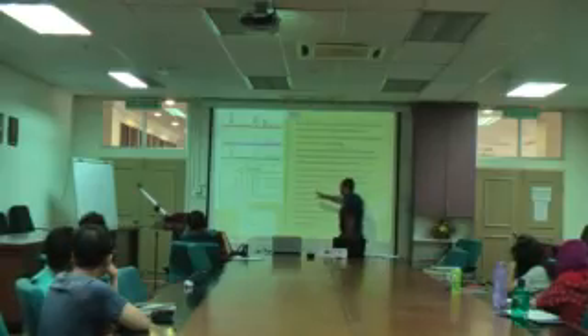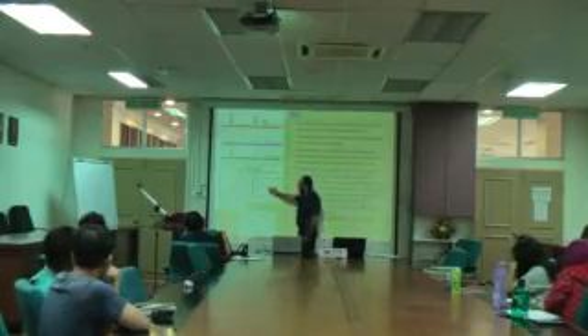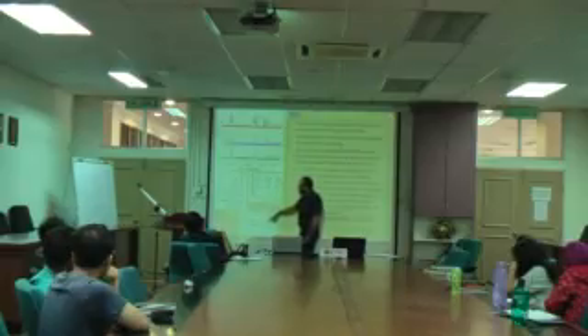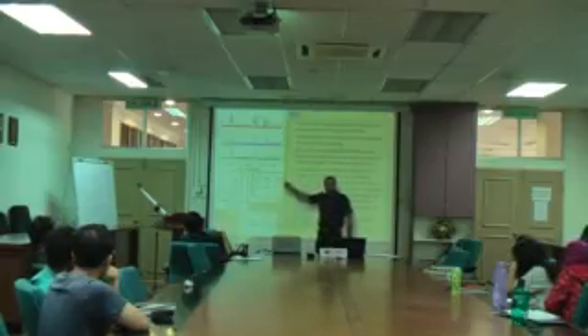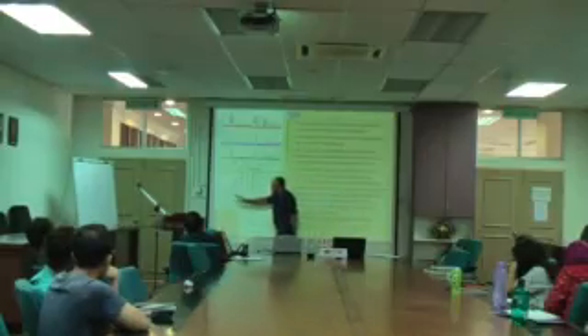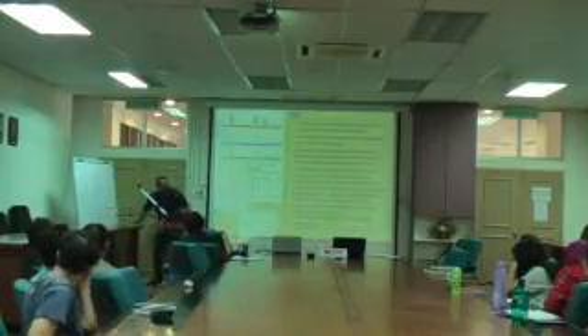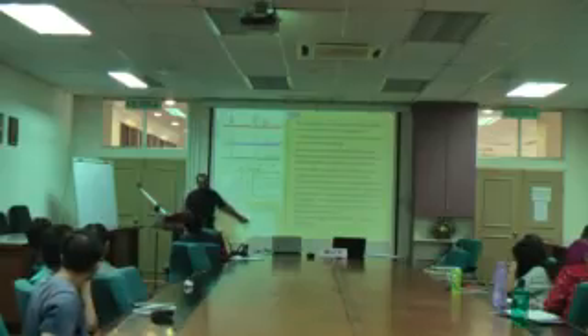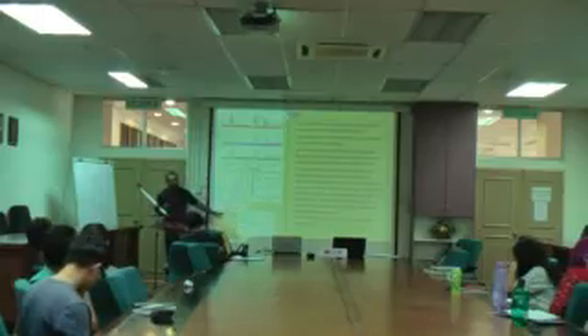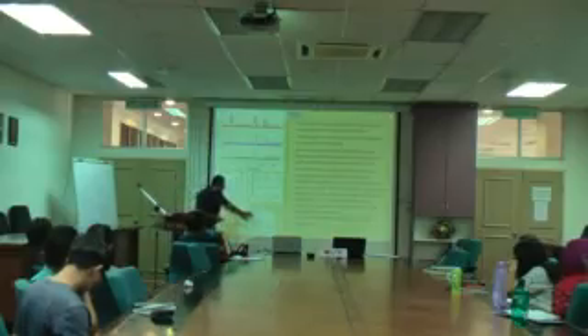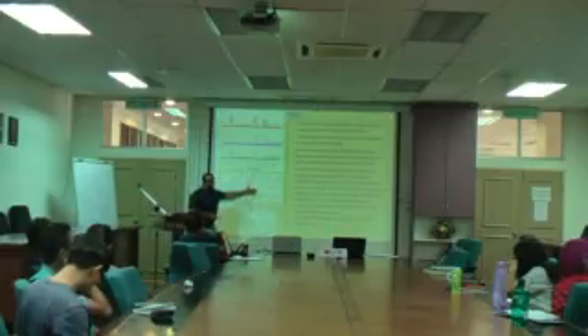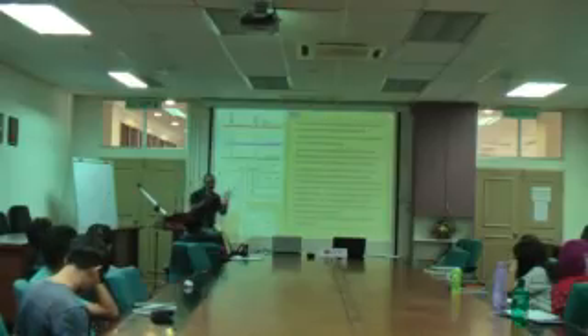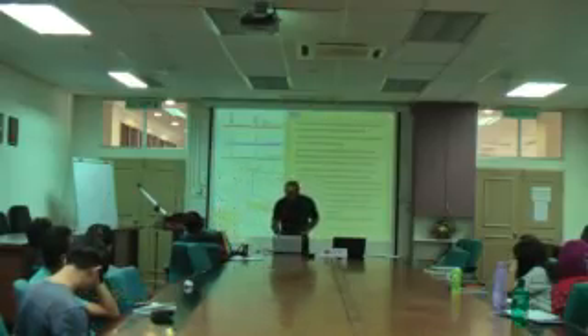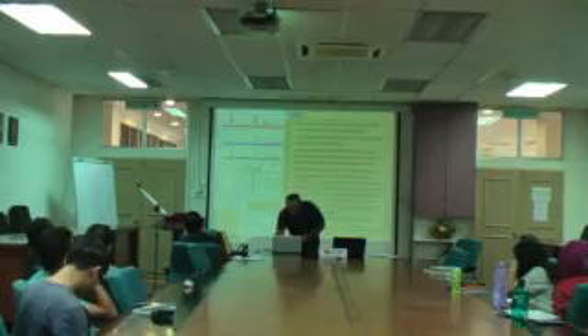And also for Scherrer, these are two different characterizations that we extracted from XRD. For Scherrer, we don't consider this one, and Williamson-Hall is the better analysis for calculating the size and strain together at the same time. Of course, this number with AFM should be all in the same range. Should not have any difference.